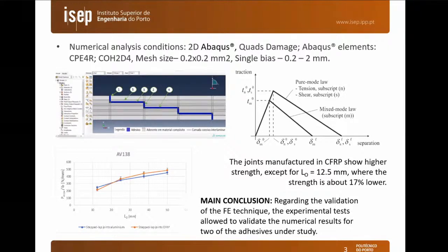We can see an example of the model considering different failure possibilities, namely failure in the steps, in the butt portions of the adhesive, the small vertical portions connecting the three steps. We also accounted for the possibility of delamination in the composite at several horizontal plane steps. And as an example, I just show here the agreement for the AV138, where I am comparing step lap composite joints with step lap aluminum joints. This was another comparison that we did.